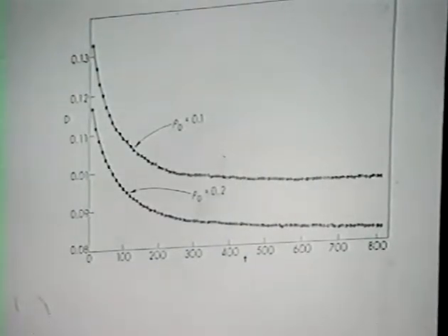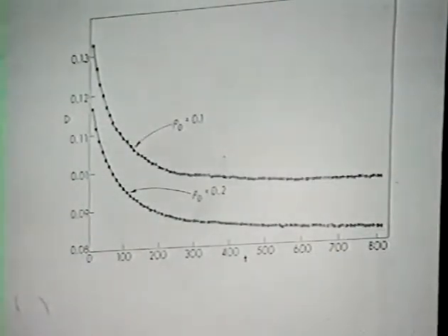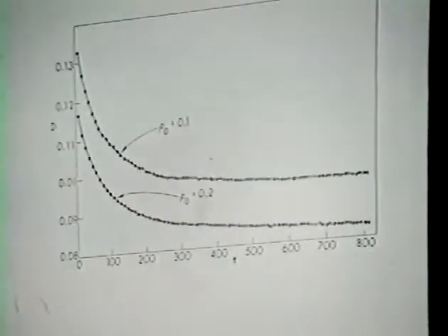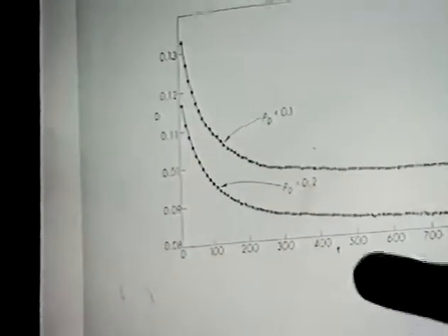And if you remember my discussion of fractals, if delta, the exponent relating mean square displacement to time, is close to 1, then the D value varies with time very, very slowly. Given that we basically have the structure of the pillar almost exactly similar to the computer, that may indicate that yes, pillar clays may indeed have a fractal structure. And that means that D varies with time very slowly.